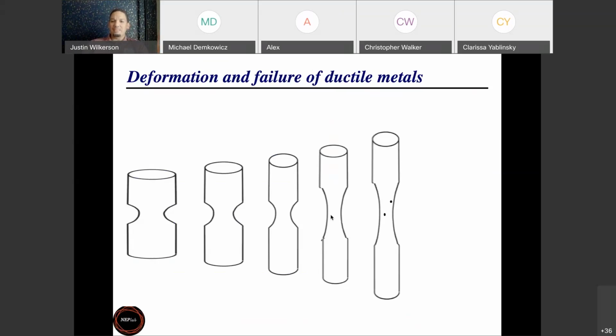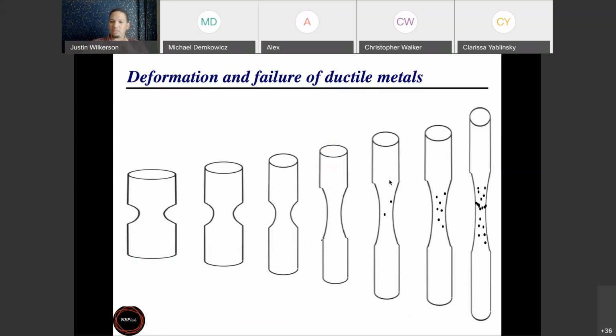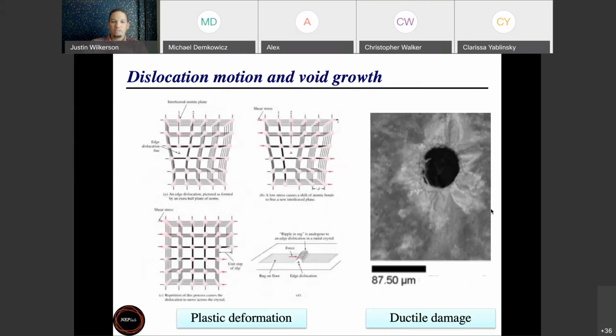It's in this fairly late stage where I first start getting nucleation of damage. So these black circles here are indicating when I'm starting to get void nucleation. So I nucleate a few voids, I continue to stretch the material, I nucleate a few more voids, and then finally those voids start to coalesce and they form a crack and the specimen breaks into two pieces at that point.